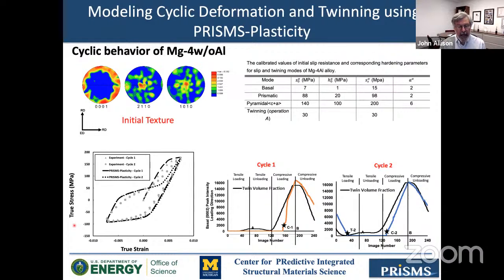We do a lot of work calibrating crystal plasticity models with this, or using crystal plasticity models to model this. And this is an example of our PRISMS plasticity code for this magnesium aluminum, showing the fidelity of our model and the experiments. Now, one of the problems, as I said, is that we can't really quantify the twin volume fraction using this particular HEDM technique. But we have a very advanced twin detwin model in the PRISMS plasticity code. And so now we can quantify the predicted twin volume fraction, and at least it lines up pretty well with Ariel's results from HEDM.